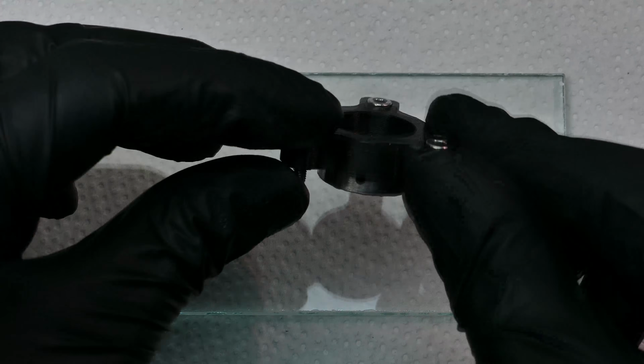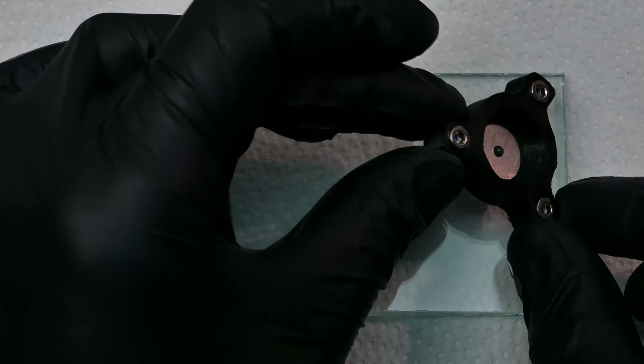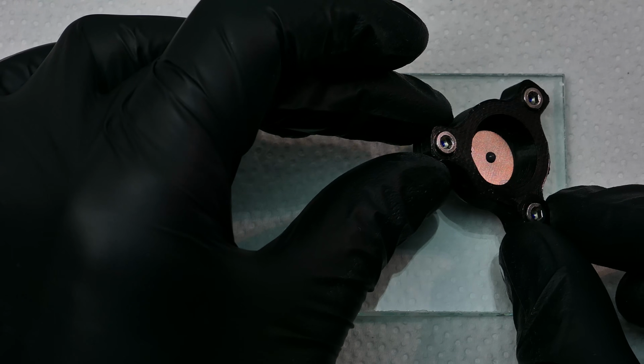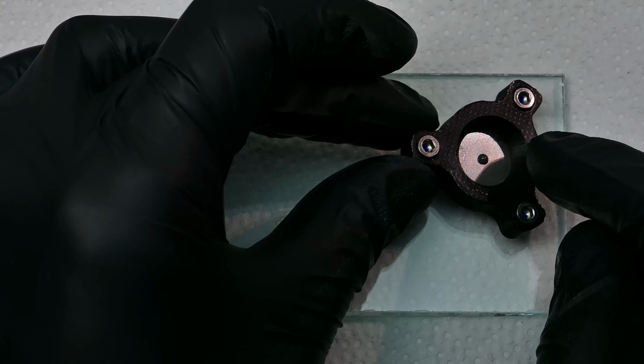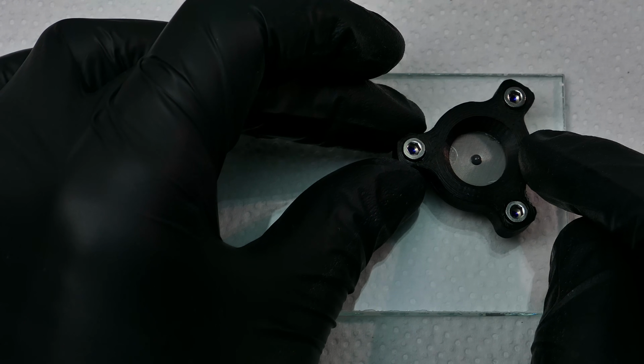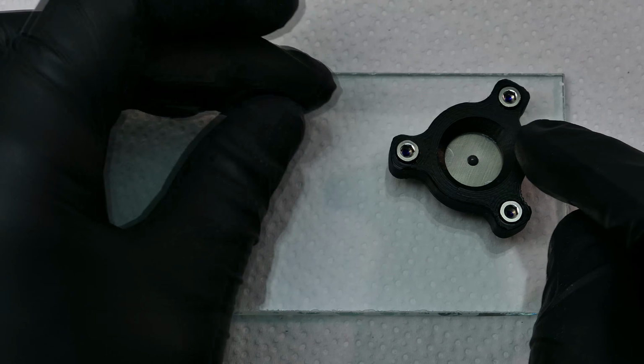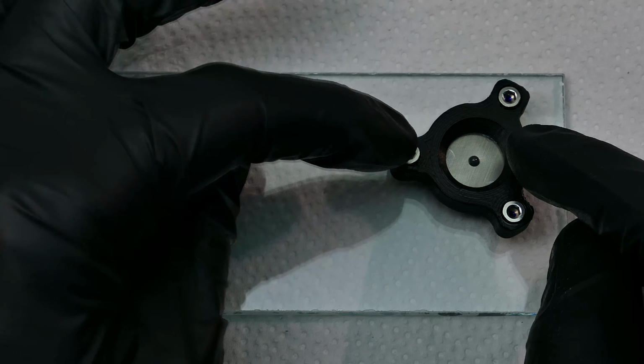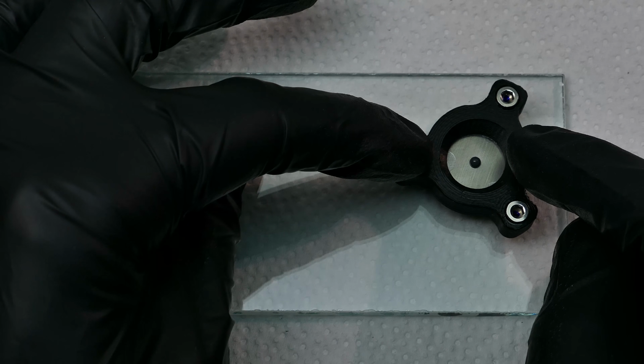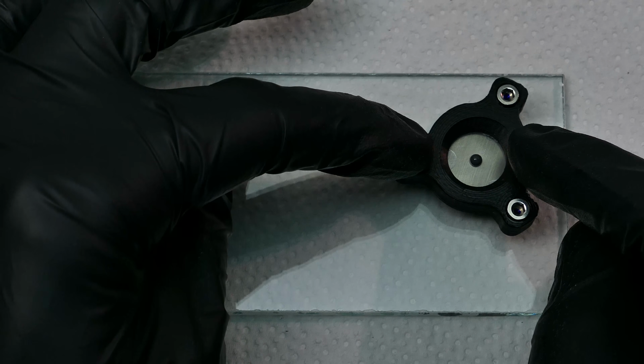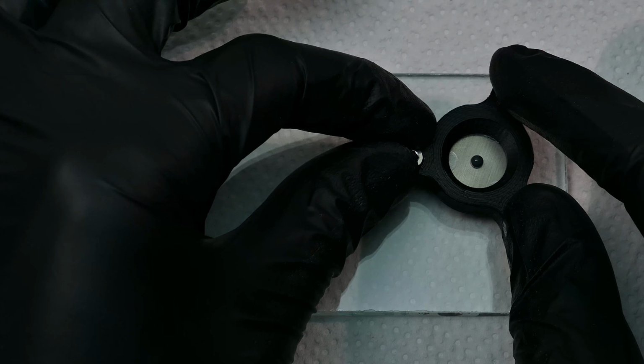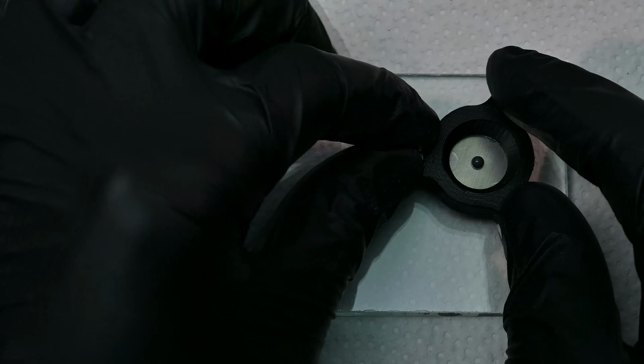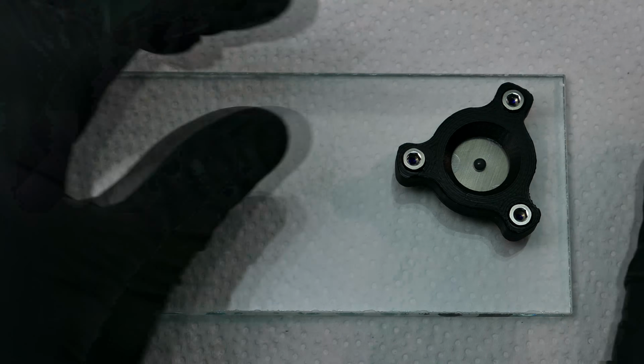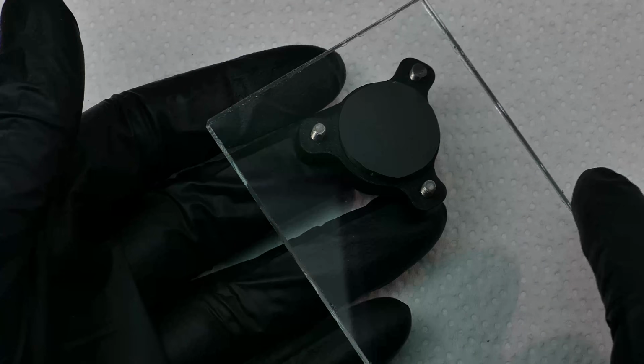Now take the molding jig with the metal disc and place it onto the prepared glass surface. To prevent air from being trapped, angle the fixture when lowering it down. Then gently push and wiggle it further down until all 3 screws touch the glass surface, giving you a precise and even film thickness. Excess resin will be pushed out the sides. You may check for voids and defects, which may form if not enough resin was applied in the previous step.